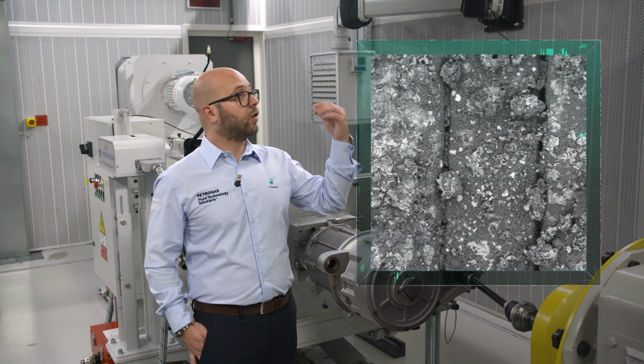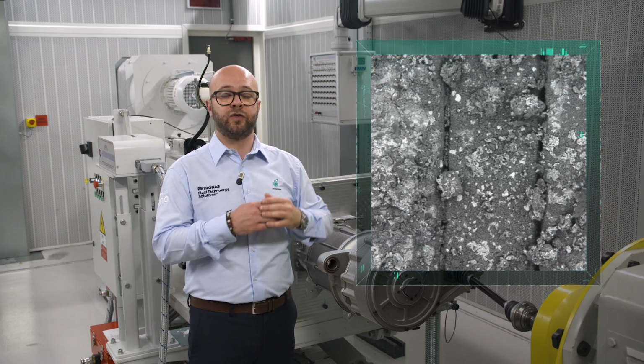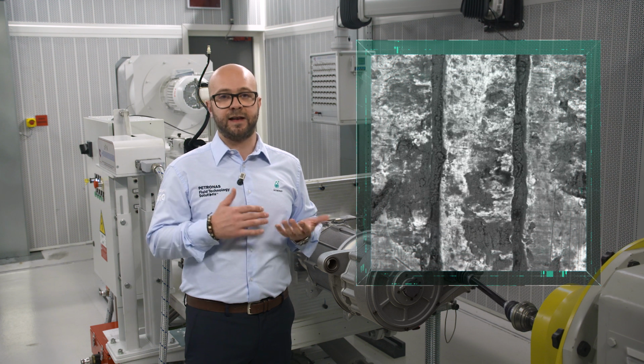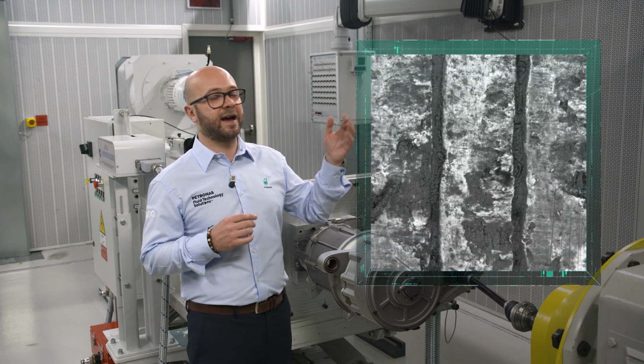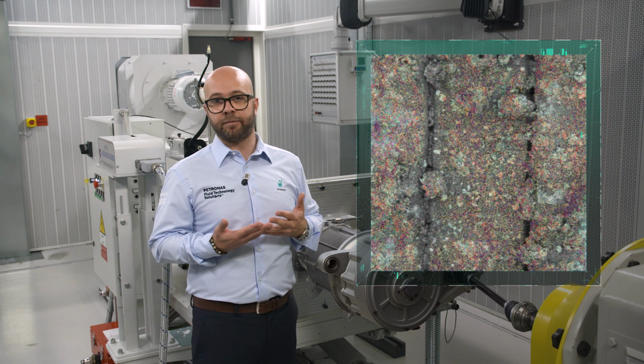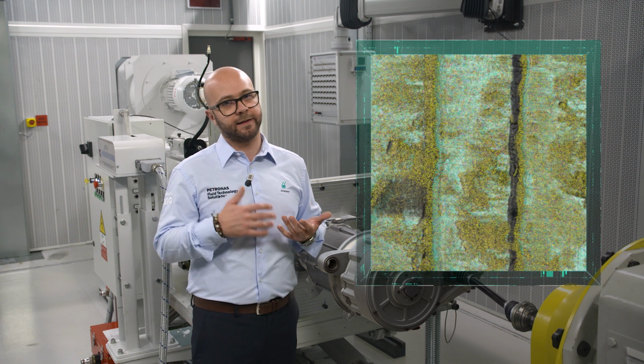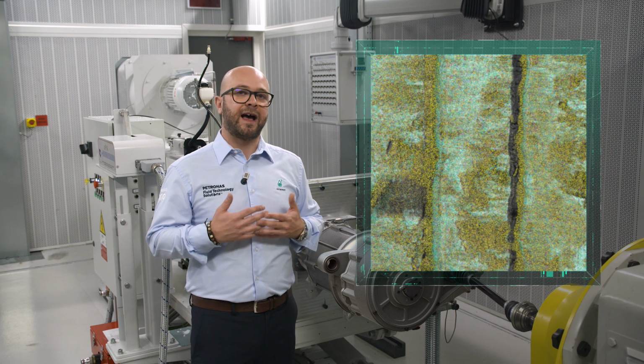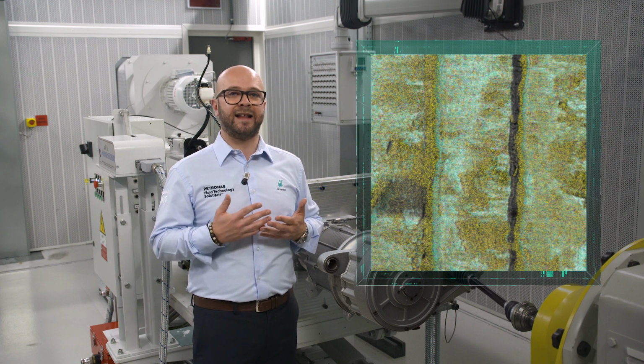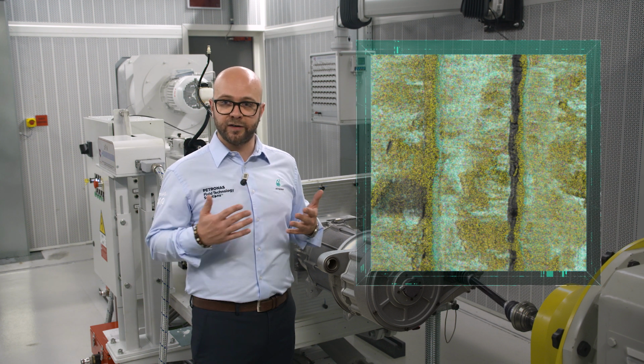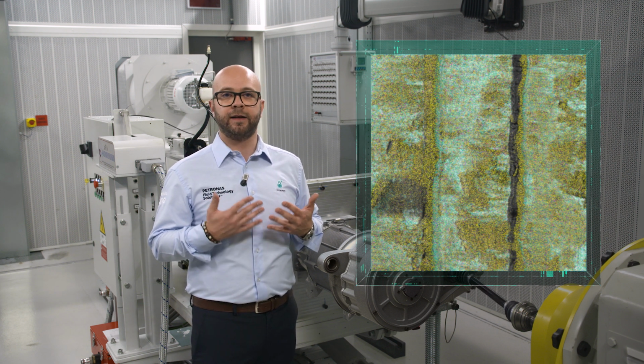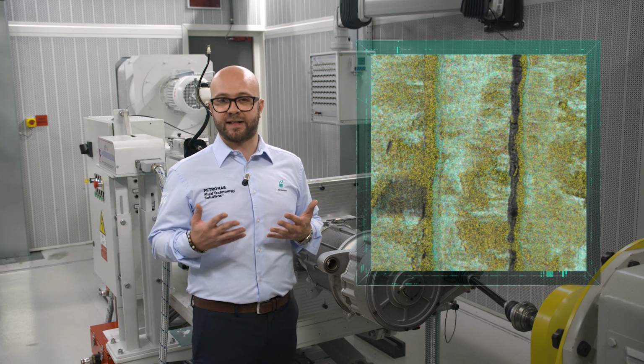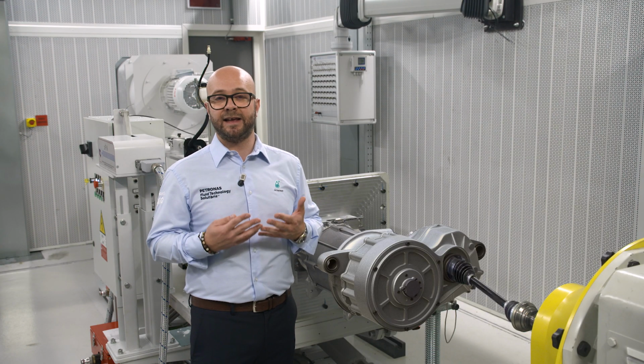Vice versa, for the exposure to the vapor and the exposure to the interface of liquid and vapor, the surface is covered by a thick layer of deposit of fluid that got vaporized on the surface. However, it is important to highlight that in all these conditions we are not able to find any issue of corrosion. We don't have corrosion attack, so we can say that exposure to pure oil is not leading to damage of the part through a corrosion process.